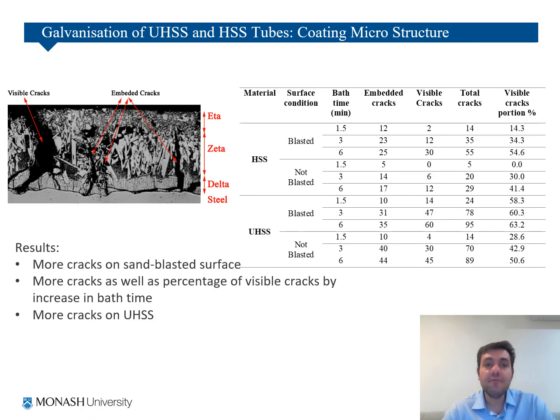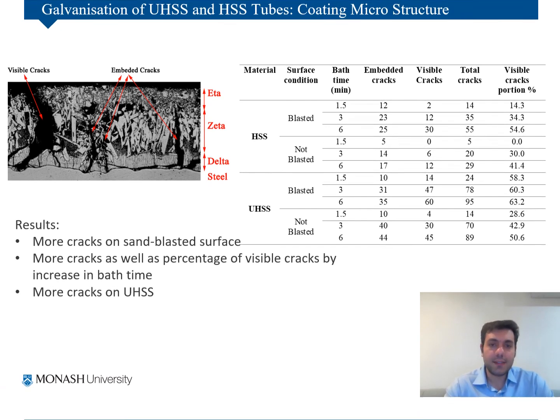Then in the bent region, we counted all the cracks. We have two types of cracks, visible and embedded cracks. We found that more cracks formed on UHSS tubes, more cracks formed on blasted ones, and more cracks formed on tubes which were galvanized for a longer time. And the visible cracks became higher for all of these. So with UHSS, blasted, and more bath time, the visible cracks increased. And visible cracks are the bad ones actually because they expose the steel substrate to corrosive environment.